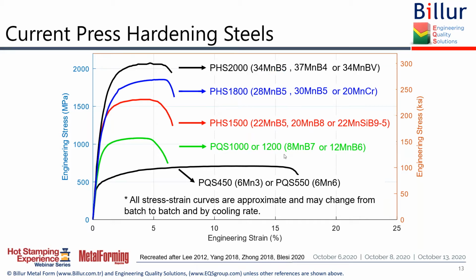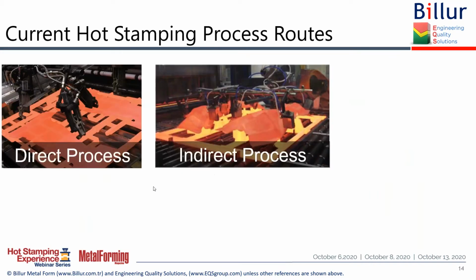These have the first 2 numbers that you see showing us the carbon level. So they have the highest amount of carbon, about 0.34 or 0.37 weight percent carbon. By the way, all the stress strain curves are approximate and may change significantly from batch to batch or by the cooling rates.